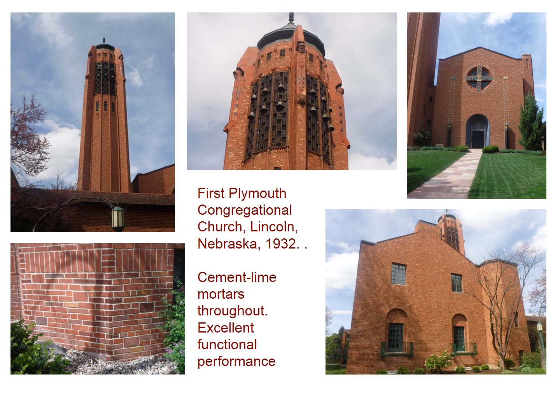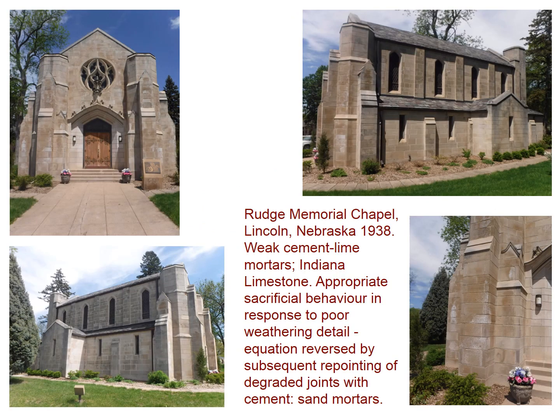And we need to mention the elephant in the room, in the lime room: cement lime mortars. There are buildings all across North America. There are buildings all across the UK, including, for instance, the new Coventry Cathedral, built throughout with cement lime mortars, and those mortars with a high free lime content are offering excellent functional performance. They are not promoting decay, even in the presence of dampness. And this is amplified by Rudge Memorial Chapel, also in Lincoln, built 1938 with weak cement lime mortars on Indiana limestone. These have displayed appropriate sacrificial behavior in response to poor architectural detailing, poor weathering detailing. But of course, well, not of course, but as it happens, where those mortars behave sacrificially, they were repointed with a cement sand mortar, and that has reversed the equation, very sadly.